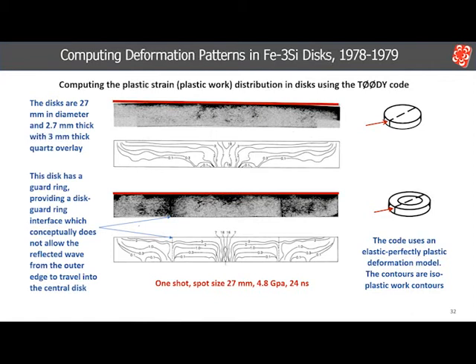Overall, where there is some agreement between the micrograph and prediction, the computation was not successful in predicting the actual strain distribution. These computations were only run through once due to the time and expense issues mentioned earlier. However, the computed results did corroborate the existence of non-uniform distribution of plastic strain observed in the discs.